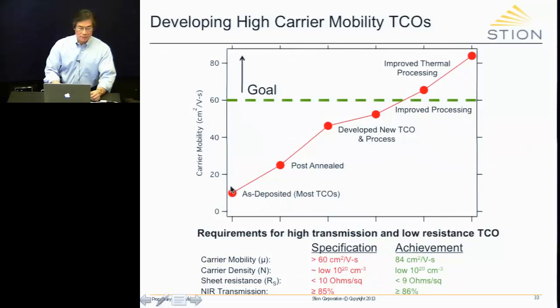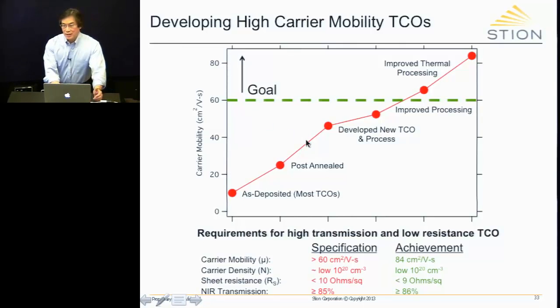Here's a plot of the carrier mobility, measured in centimeters squared per volt seconds, as a function of the different things that we've done to it. Our goal actually is to get to 60 or above centimeters squared per volt seconds. Now, most TCOs, when you deposit them, like AZO, for example, is around here, about 10, 15 centimeters squared per volt seconds. That's horrible. It's absolutely horrible. It will not work.